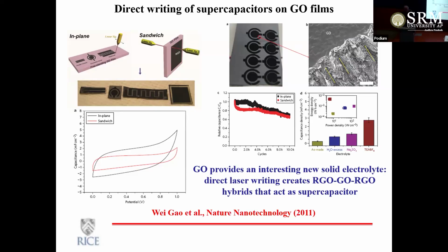In fact, the first experiment we did in this was much simpler. We took a graphene oxide layer, which is basically oxidized graphite, and made a thicker film, and then locally changed the oxidation in the regions by using a laser beam. So basically laser patterning, right? Go across the film and essentially reduce locally the graphene oxide into reduced graphene oxide.